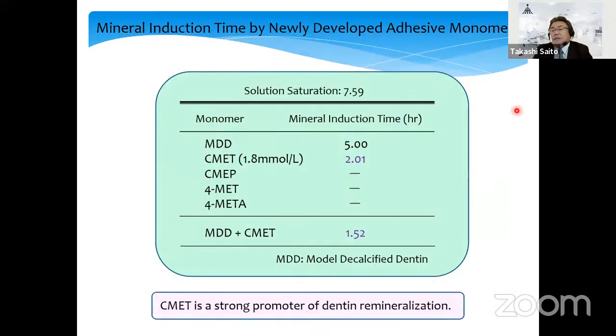We measured mineral induction time. In the case of MDD, which mimics the carious dentin, it was 5 hours. For CMET, it was only 2 hours. Compared to model decalcified dentin, CMET induced mineral formation very quickly. Then the combination of MDD and CMET shortened the mineral induction time to 1.5 hours. According to the result, CMET was suggested to be a strong promoter for dentin remineralization by providing a source of calcium ions.